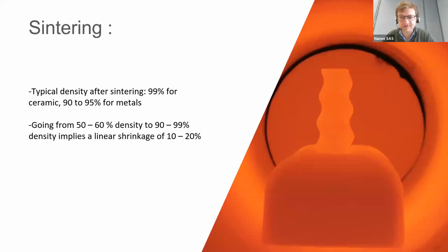Then we go for sintering. Sintering usually gets to high densities for ceramic, typically in the range of 99%. With metals, we are a bit more limited. We will reach 95% in ideal conditions. We feel it's good enough for the applications we have for this material, but you should be aware of that. Of course, having such a densification means you'll have shrinkage. In the case of metal, it's not precise here, but it is in the range of 15% of shrinkage. And you will need to compensate for this in the slicer. That's an absolute necessity.